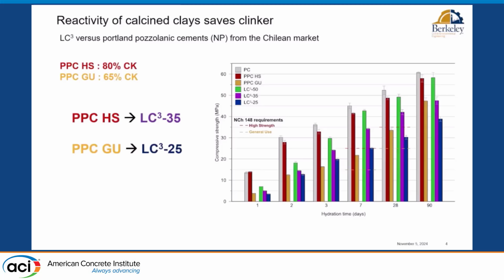And what we found is that in order to match what the standard prescribes for high strength, remember 80% clinker factor, when you do that with natural pozzolans, you only need 35% clinker if you do it with calcined clay. Why? Because the calcined clays are more reactive. And if you only need the general use performance, actually you only need 25% clinker factor in that material. So in essence, what we demonstrate in this study is that you can save between 40 to 45% clinker when you use calcined clays. I would say not really LC3, but calcined clay as compared to natural pozzolanic, just in the difference of reactivity.